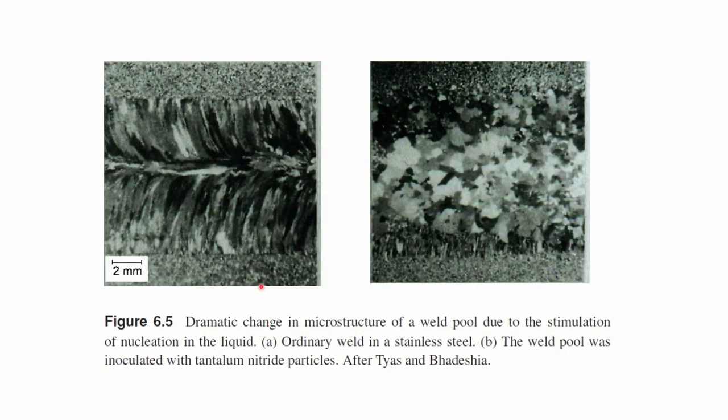Here I give you one example talking about materials. The figure on the left is the process during welding without any additional particles inside. The one on the right side, we have on purpose added tantalum nitride particles inside. Then these work as seeds to help the heterogeneous nucleation to get a smaller grain size, also uniform, and also isotropic properties.